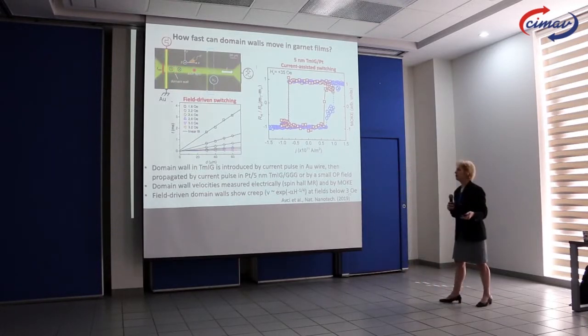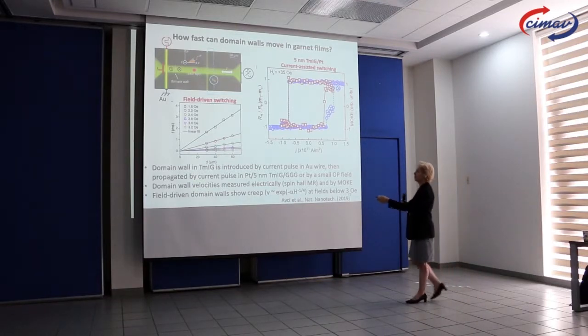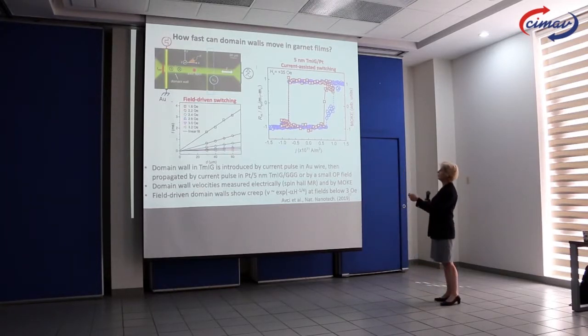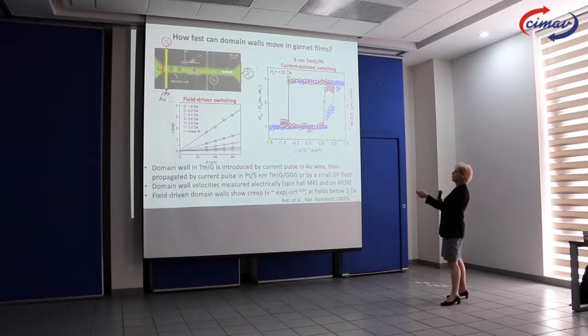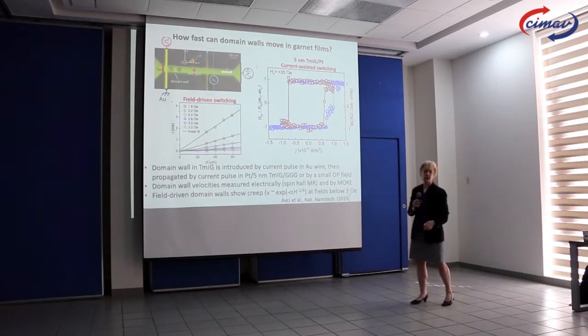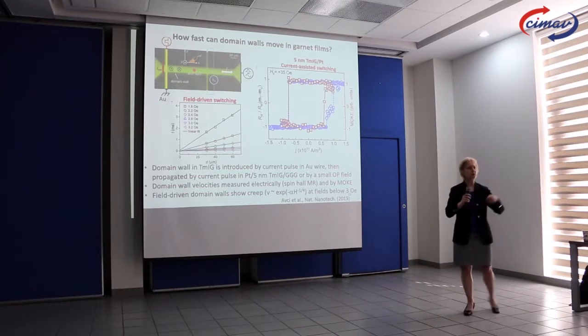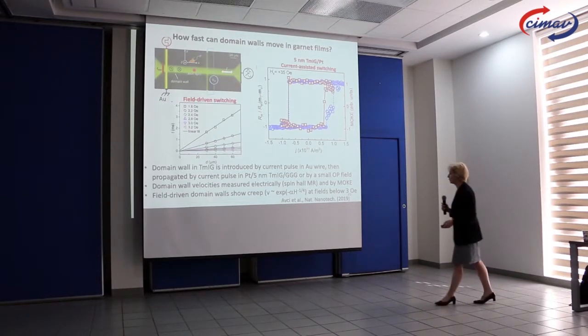So we can look at different phenomena like how much field does it take to move that domain wall? Well, it moves in fields of a few Ørsteds. It's a very low pinning material. How much combination of field and current does it take to move the domain wall? Well, we can measure that as well. In this case, 35 Ørsteds was applied in plane, and the garnet switched at a current density of about 0.7 times 10 to the 11 amps per square meter. So you can probe all the conditions that lead to switching.